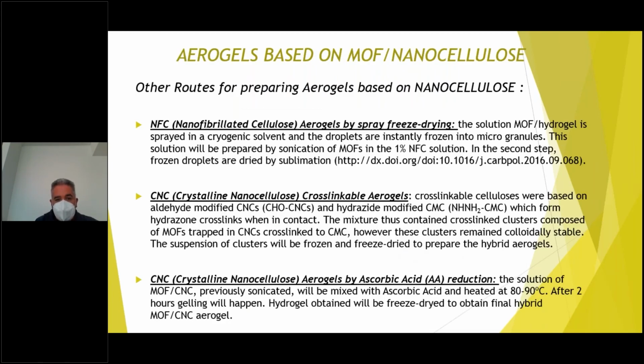Well, the idea of introducing these aerogels is to prepare MOF in aerogel structures with a polymer. The polymer that we are using as support of this aerogel structure is nanocellulose. Several routes are well described to prepare aerogels based on nanocellulose. For example, we can use nanofibrillated cellulose or crystalline nanocellulose. In the case of nanofibrillated cellulose, we can prepare aerogels by spray freeze drying processes. In the case of crystalline nanocellulose, we can use cross-linkable aerogels using, for example, hydrazide that can make this bonding between the cellulose